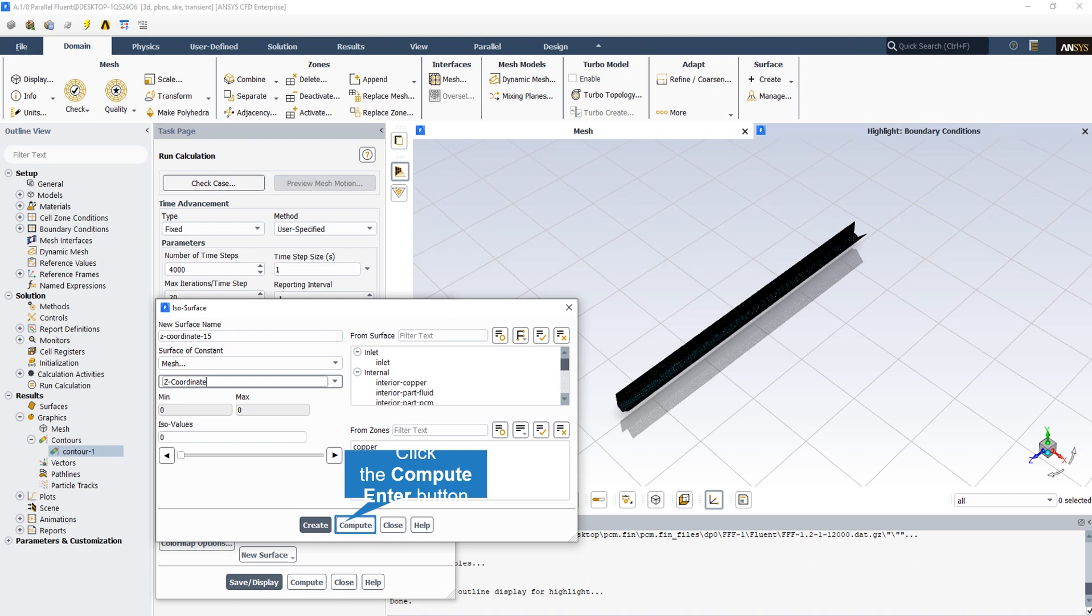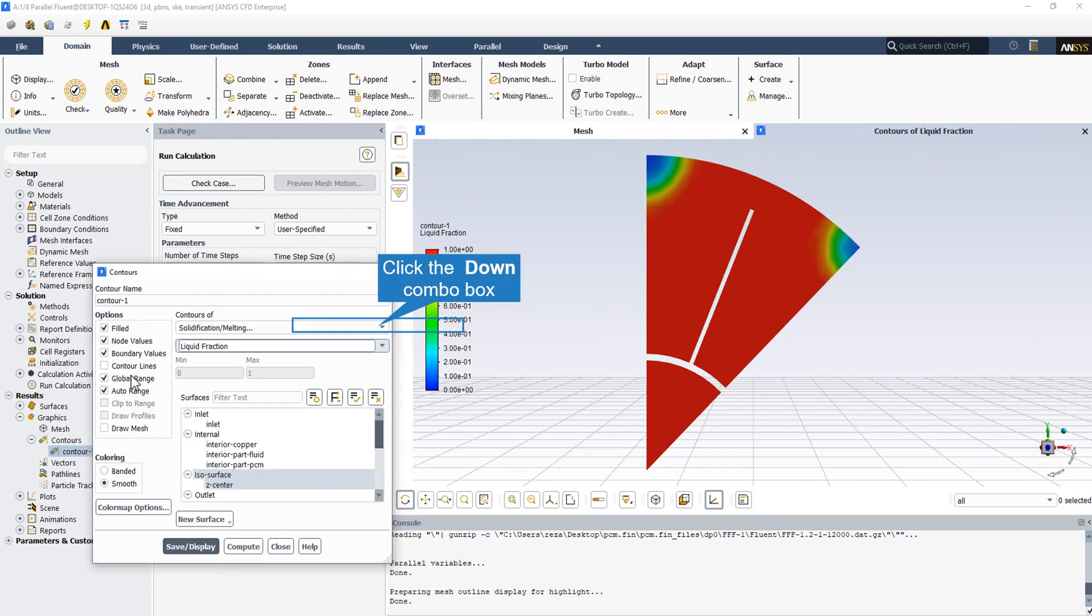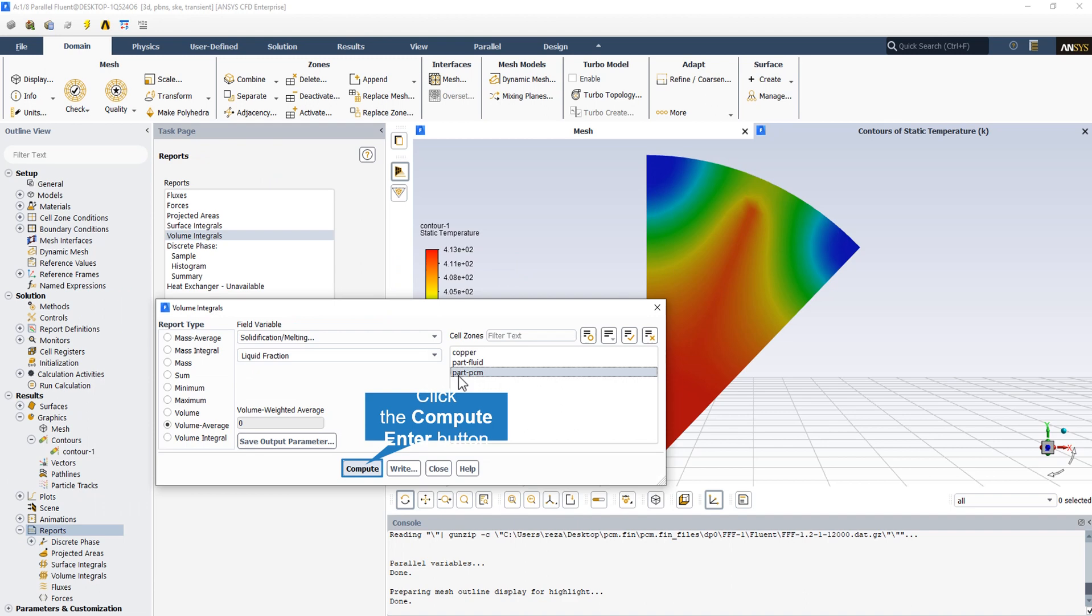Select the mesh, the button of Surface of Constant, and then select the Z coordinate. In this order, we can make a Z-constant surface in the whole domain. This is the solidification and melting contour, and this contour shows the liquid fraction. As you see in the corners, the liquid fraction is equal to zero, meaning there is still solid in the corners. All other parts of the domain are melting and are completely liquid because the liquid fraction is equal to one in almost all of the domain except the corners. Following this procedure, we can obtain the volume average of the liquid fraction in the PCM part.